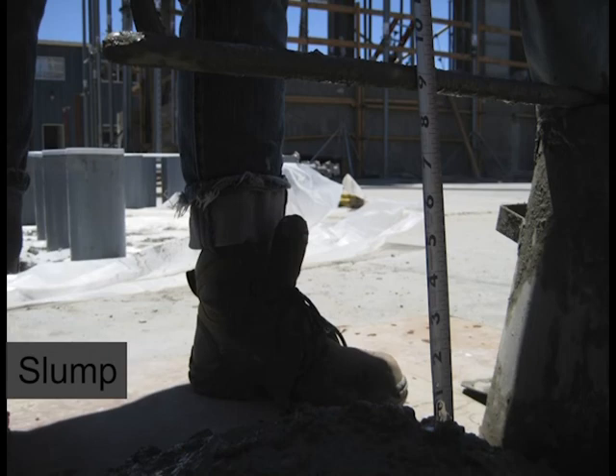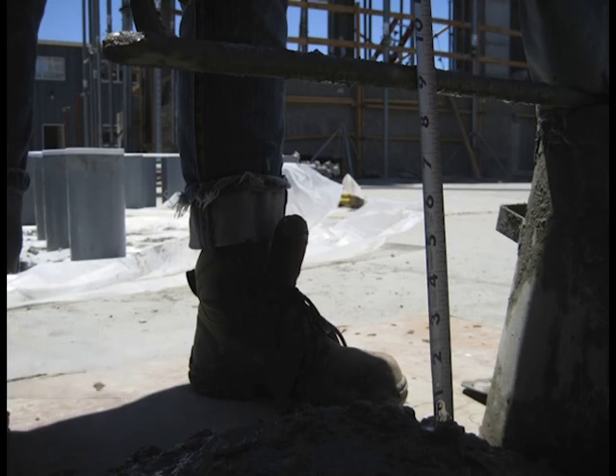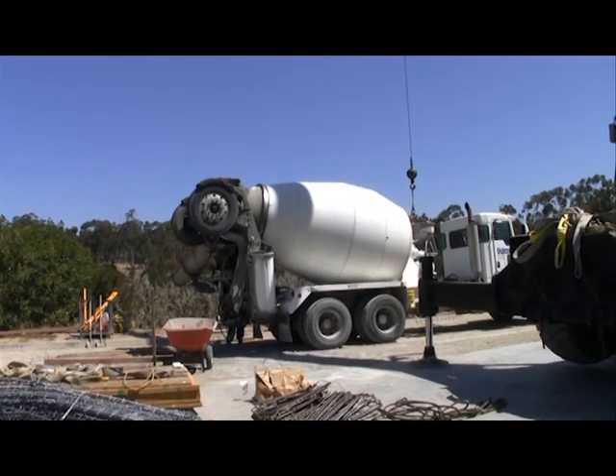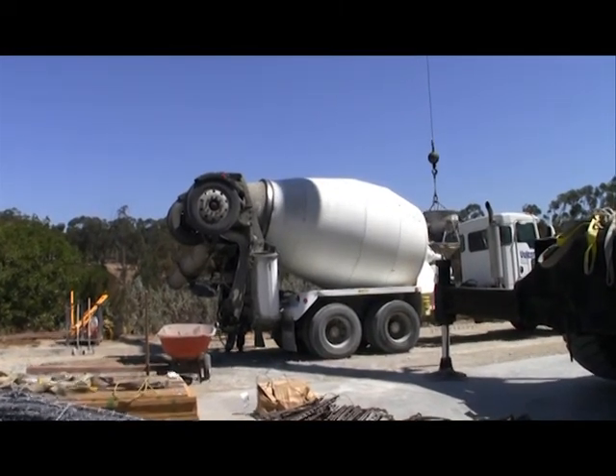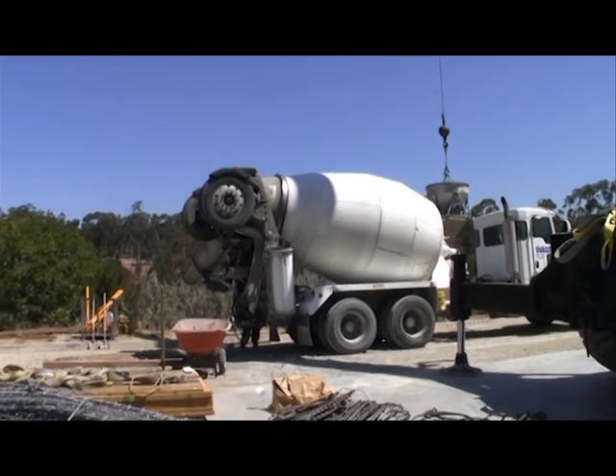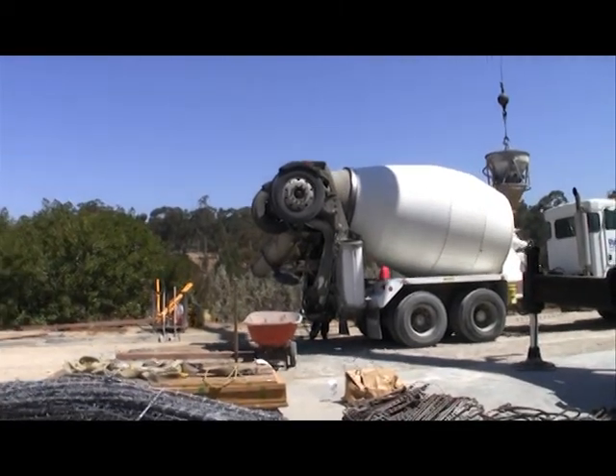The change in height of the concrete sample is referred to as the slump for that specific batch of mix. The slump measurement is compared with specified values, and a decision is made to accept, modify, or reject the concrete mix before placing the concrete. In the five-story building construction, once the desired concrete mix was attained, the concrete was poured into the formwork using the truck-mounted boom pump method.